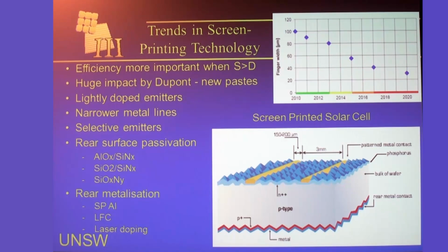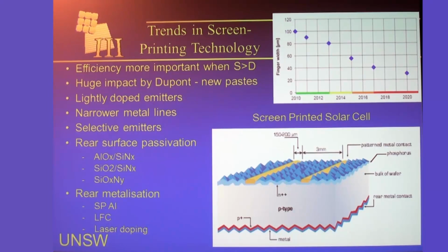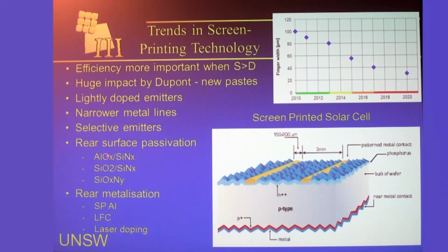In other words, they put down their dielectric passivating layer, they then pattern that dielectric layer, such as with a laser, and then they screen print a lower temperature aluminium paste onto the rear surface that they fire at something like 700 degrees Celsius. That enables the ohmic contact to be made to the P-type silicon, forms a crude sort of back surface field P+ region in those localized areas, and then in the remainder of the area, the silicon nitride protects the aluminium oxide from that screen-printed aluminium layer.